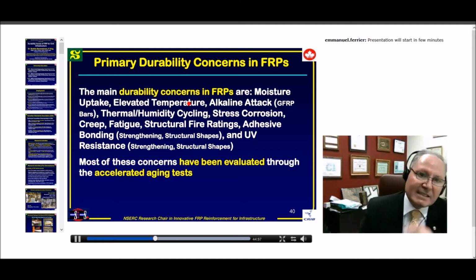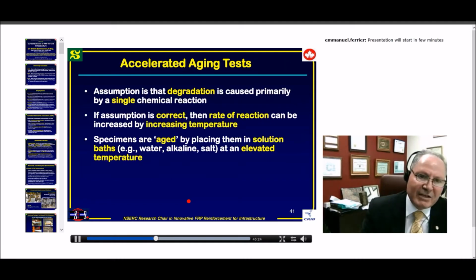Of course, by addressing this in the lab, we have to generate data for long-term behavior. We cannot build structures and wait 75 or 100 years to know if the material is durable or not. So in general, during the last few years, researchers developed what's called accelerated aging tests, mainly by accelerating the degradation using elevated temperature.